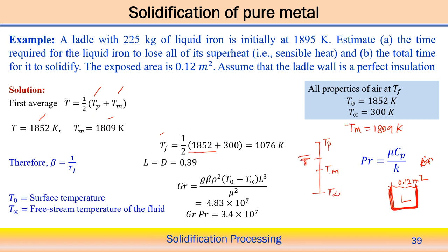So, when you consider this one, we can take the average temperature T bar, and this is T infinity, the air temperature. We can calculate the film temperature, accounting for T infinity, the air temperature, between these two we can make another average, 1852. So, T bar and T infinity, the average of that is 1076 Kelvin. This we can calculate as the film temperature TF, because we need it to estimate the volume expansion coefficient. This beta can be estimated like that, 1 by TF. So, 1 by TF indicates the volume expansion coefficient that we can estimate.